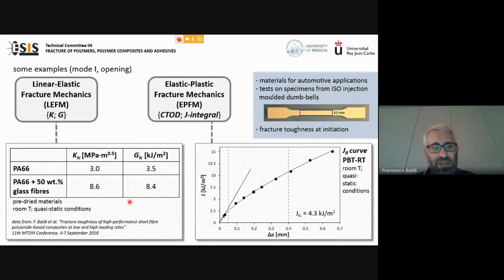C means that it's at fracture initiation, for a polymer 6,6 and for a compound polymer 6,6 with 50% of glass fibers. We can read that for the polymer 6,6 I have a value of K1C that is around 3 megapascal per square root of meter, whereas for the compound... But the number is not important in this context. What is important is that I succeeded in the application of a linear elastic fracture mechanics developed for time-independent materials to polymers.